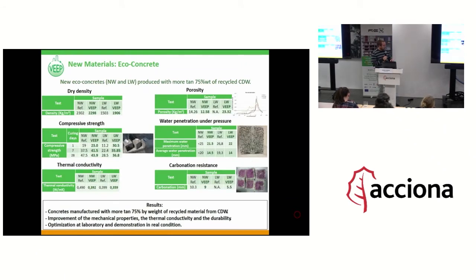Here you can find some results of the hardened properties and durability properties of the new concrete. We observed that, for example, the compressive strength was improved at early age because of the addition employed in the formulation. And the durability was also improved compared to the reference one. So we have developed a new concrete with more than 75% of recycled material, and we managed to improve some of the properties of the material compared to the natural one. The most difficult thing in this kind of materials is the durability, to obtain good, satisfactory durability properties, and in this case, the water penetration and the carbonation resistance were lower than the reference one.